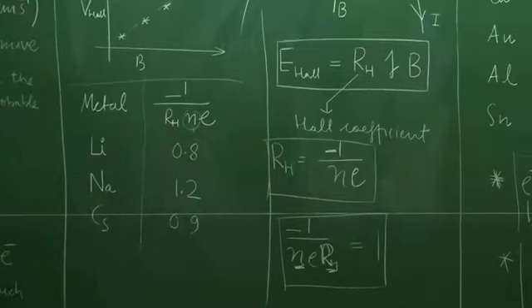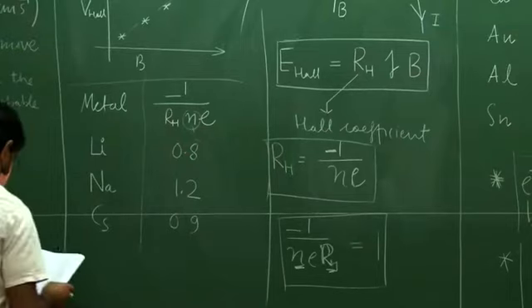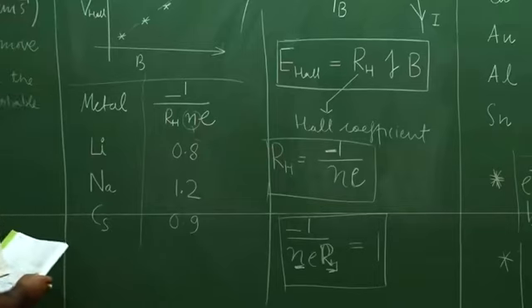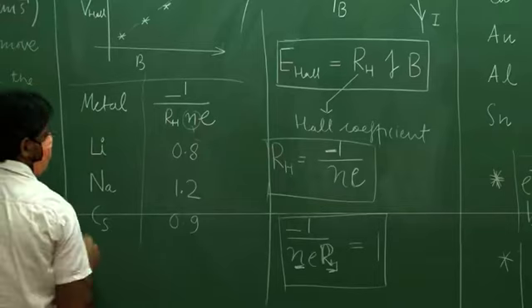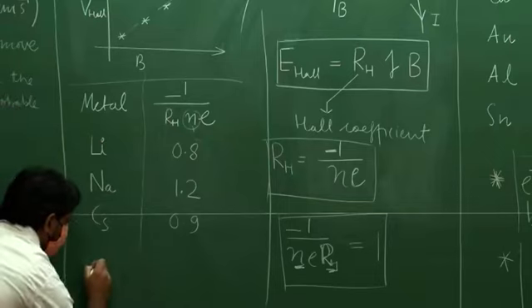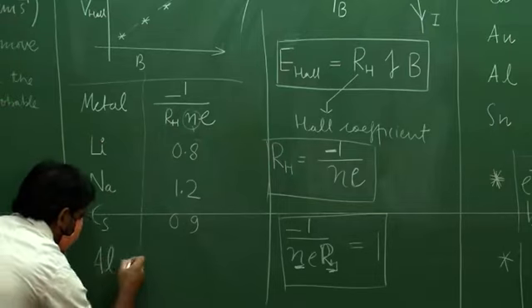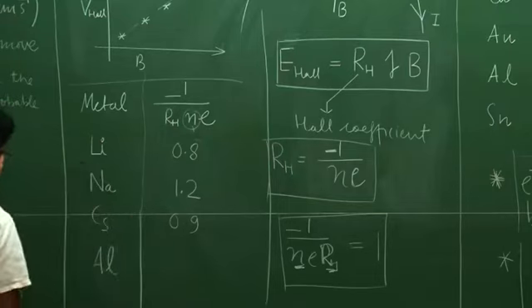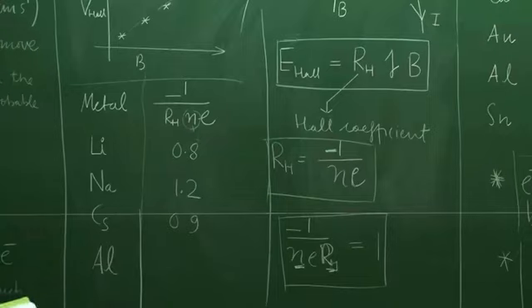But there are surprises. Now what are the surprises? The surprise is that if you perform the Hall measurement on aluminum, a very simple metal which is readily available, as opposed to cesium, sodium and lithium. Sodium is also easily available, but it is not very stable in air. But aluminum is, and you can do the measurements in lab. If you do Hall measurements on aluminum, you will be shocked.